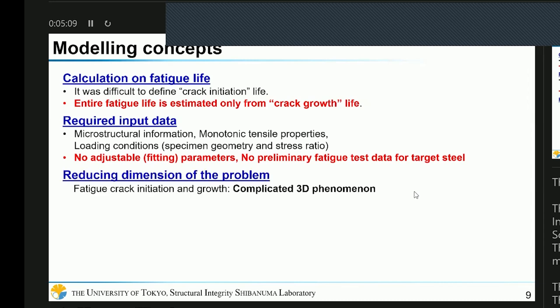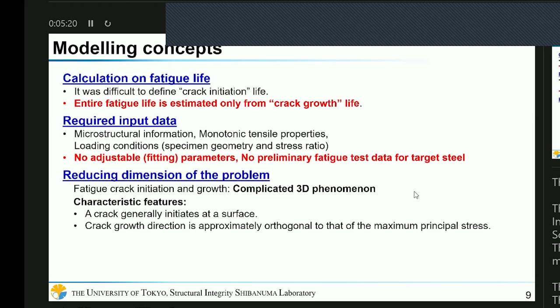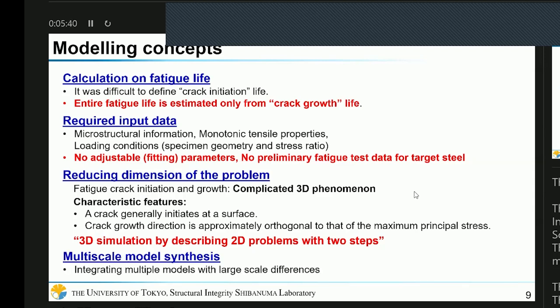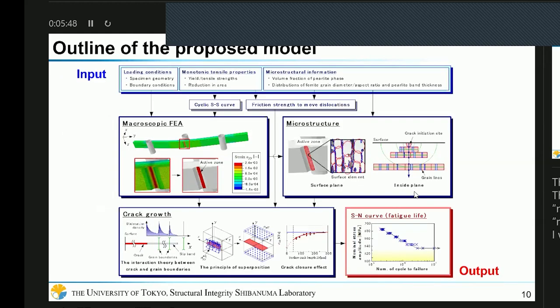And the third one is the dimension problem. Actually, the fatigue crack initiation and growth is a very complicated 3D phenomenon. However, we already know some characteristic features, such as a crack generally initiates at the surface, and the crack growth direction is approximately orthogonal to that of the maximum principal stress. So we developed a model, a 3D simulation, by describing it as a 2D problem with two steps. And the last one is multiscale model synthesis, which is an approach integrating multiple models with large-scale differences. So this slide shows the outline of the proposed model.